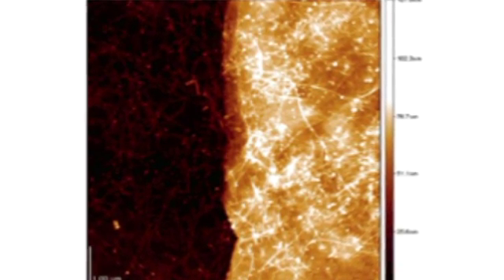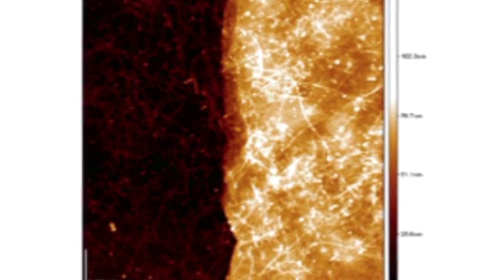This is all done in a vacuum chamber, evaporating the metals onto the substrate. The photoresist is then removed with a liftoff process. Finally the single wall carbon nanotubes are spray deposited to form the resistive network for gas sensing.